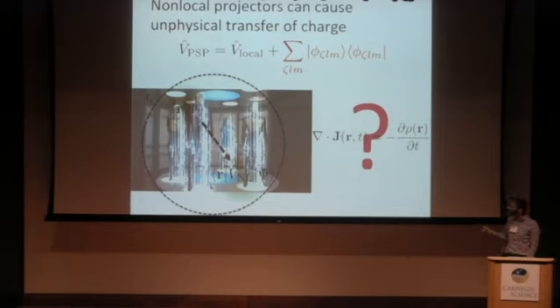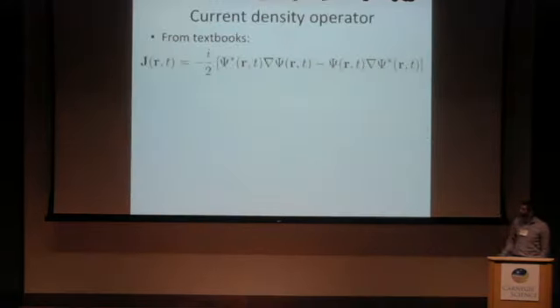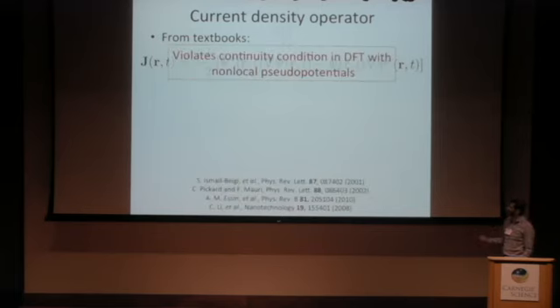And so what we have to do is to make sure that when we define a current density, it still satisfies the continuity equation even with the possibility of these teleportations. So it turns out that this definition of the current density actually does not satisfy the continuity equation when these non-local potentials are present. And so we need an alternative definition of current density in this case.